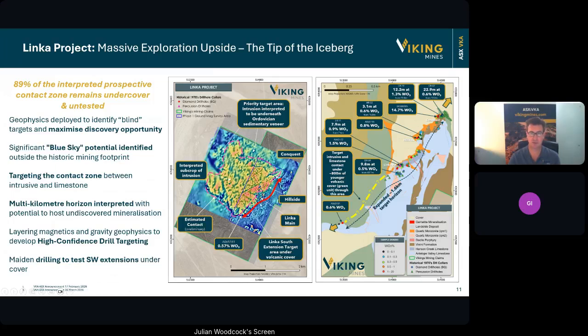If we just move to the map on the left-hand side, this red arrow represents that 1.6 kilometers. The background image is the magnetic geophysics which we completed, and we believe from that geophysics that we've potentially identified the limits of the intrusion, which is the orange rocks on the map on the right, which is a large intrusion which has a circumference of about 7 kilometers.